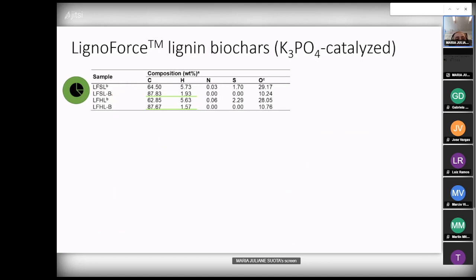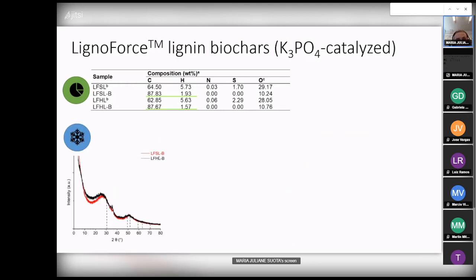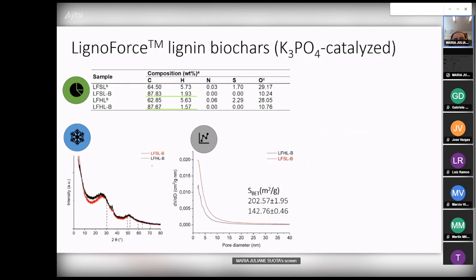As we can see here, both biochar coming from softwood lignin and hardwood lignin were rich in carbon. And as Dr. B said before, synthesizing biochar is a wonderful way to store carbon and decrease global warming problems. So we can use biochar this way, or even in other strategies I will show you later. And here, after XRD analysis, we identified no crystallinity in this biochar. It's a totally amorphous material, which is not bad, considering it is a biochar.